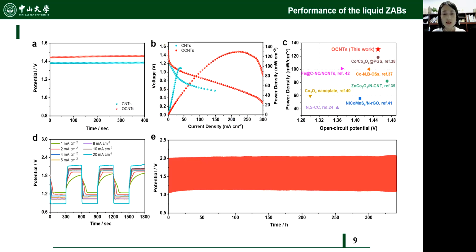The discharge curves showed the zinc-OCNT batteries possess a higher discharge potential plateau and lower charge potential plateau than zinc-CNT batteries, indicative of the better round-trip efficiency of the zinc-OCNT battery. Impressively, the zinc-OCNT battery also displays long-term cyclic durability, with negligible voltage gap change after 314 hours of charge and discharge test.